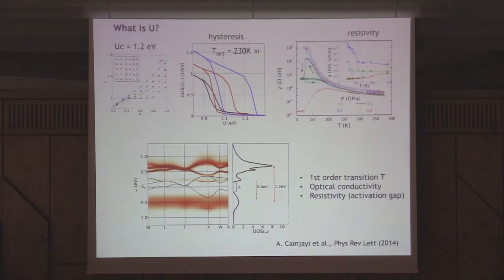So I remind you, this theory has ingredients which are in the scale of the electron volts. It's 10 to the 4 Kelvin, and we are making a prediction 2 orders of magnitude below with a very simple LDA plus DMFT calculation. So the fact that this thing extended to 100 Kelvin is not so bad. This should depend a little bit on the pressure. It's impossible to do fine-tuning of this. It was a miracle that he got that.